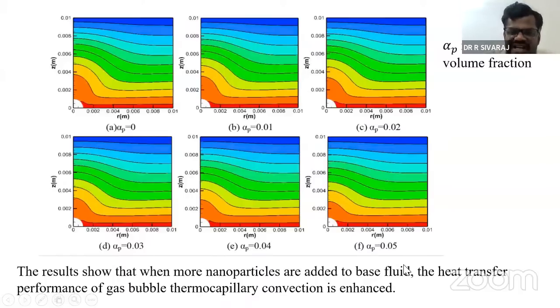So the suspension of nanoparticles effectively works as a coolant that removes the heat from the hot surface, and it makes more space of the cavity cool. This enhancement may not continue for further increases like 5, 6, 7, 8, 9, 10, whatever the increase. Up to a certain range, in most cases up to 5% suspension of solid particles into the base fluids, it enhances the thermophysical properties. Later it will decrease. We also see those results over here.